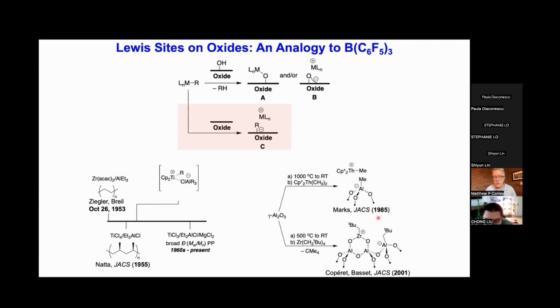That was first shown by Tobin Marks in the 80s. This paper was published about 6 months before the isolation of the bis-Cp zirconium methyl THF adduct, cationic THF adduct, by my PhD advisor. You can also do this with alumina dehydrated at lower temperatures too.